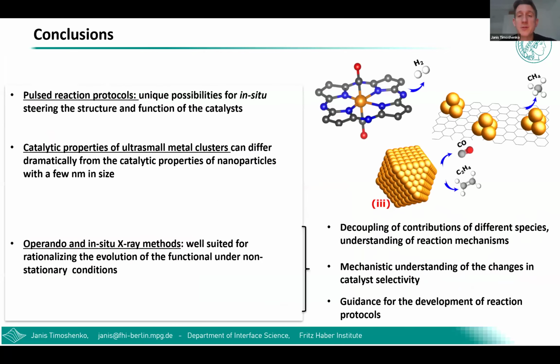Pulse reaction protocols, these non-equilibrium reaction protocols, are really a nice and new trend for steering the structure and function of the catalyst, but of course it requires some guidance from operando spectroscopic techniques. In this particular case, we have demonstrated that by going to this regime of ultra small metallic clusters, we can get properties which are typical neither for larger particles nor for single atom sites. So we can get very unique functionalities just by playing with the parameters of our experimental protocols.